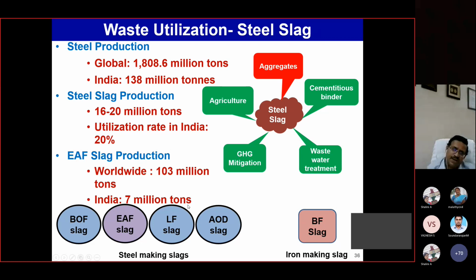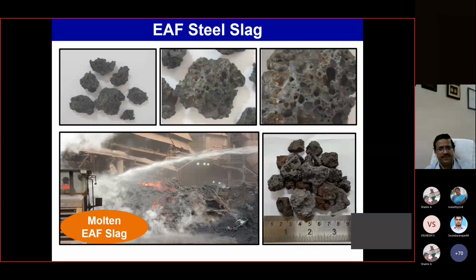We worked on both areas, to utilize it as coarse aggregate and as a cementitious binder, and successfully demonstrated. This is electric arc furnace slag, and its specific gravity is very high. It varies from 2.8 to 3.2. So it will not be very good in the building sector, but particularly for marine structures and the road sector, it can be a very good material.